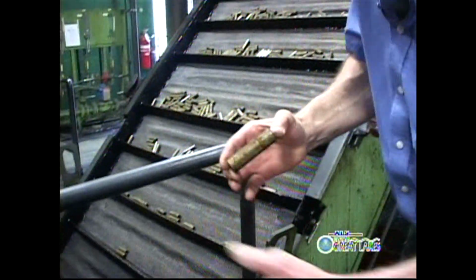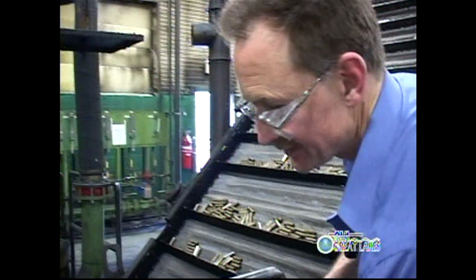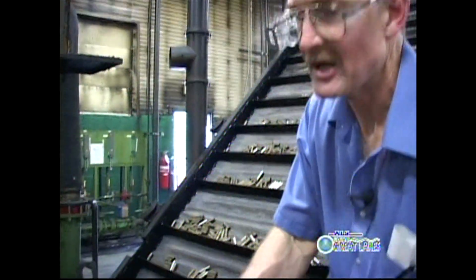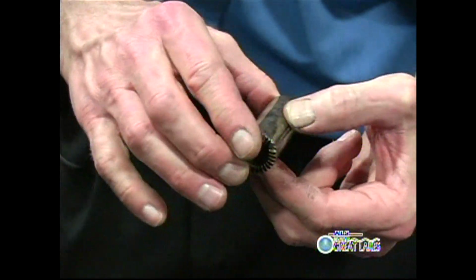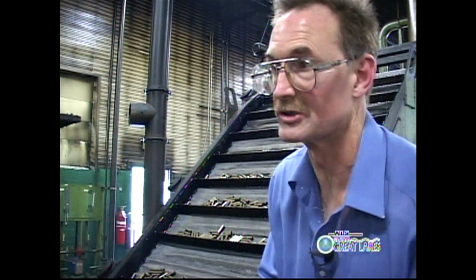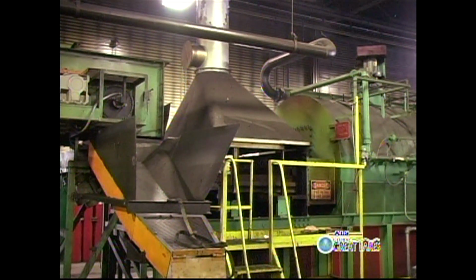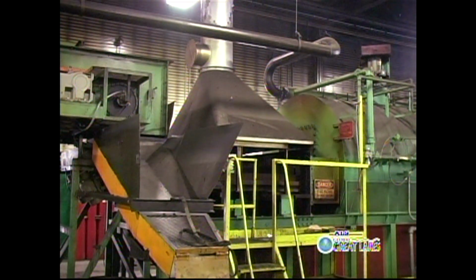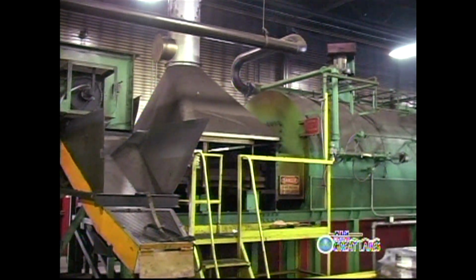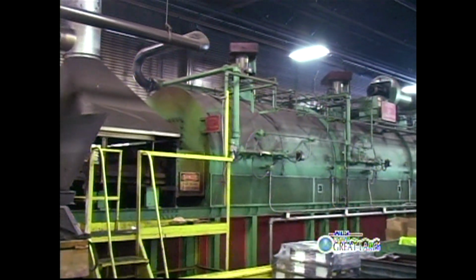This is one of the parts that has fallen into the quench and come up approximately 15 feet. As you can see, it's about 110 degrees right now. It's in the hardened condition because it has cooled so rapidly. Through the wash system and onto the tempering belt where the parts will travel to a temper. They'll be tempered for 250 degrees Fahrenheit for what the job requires.